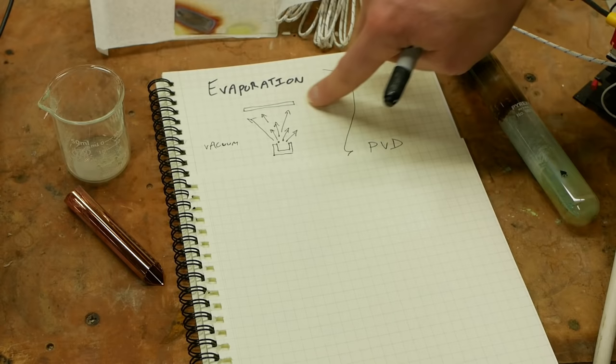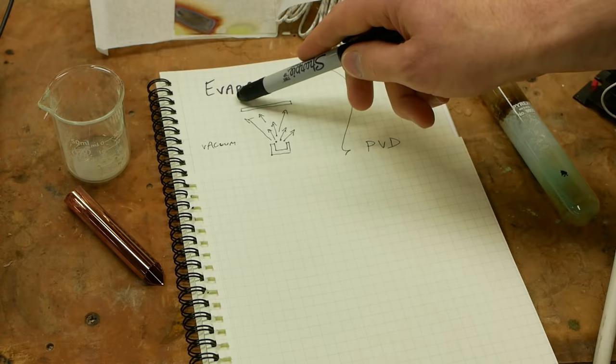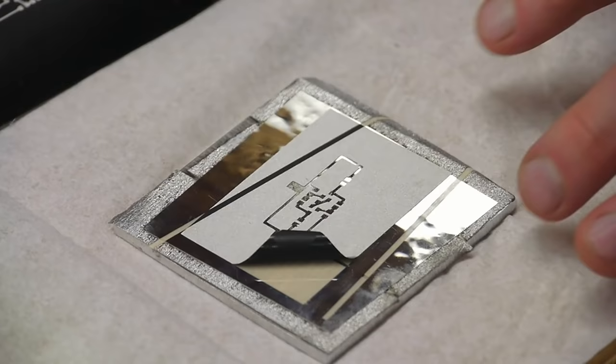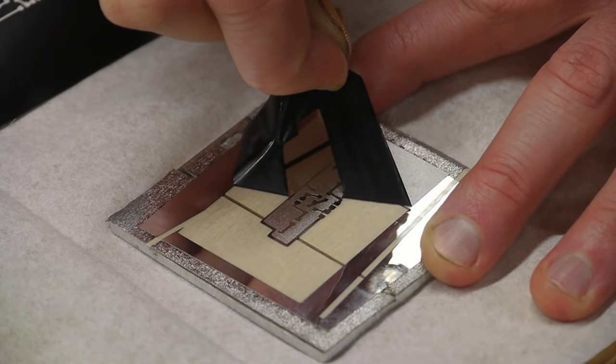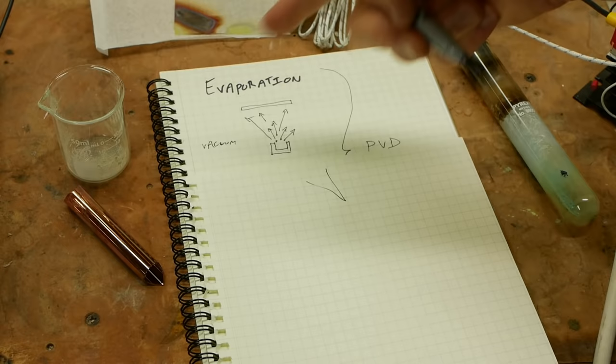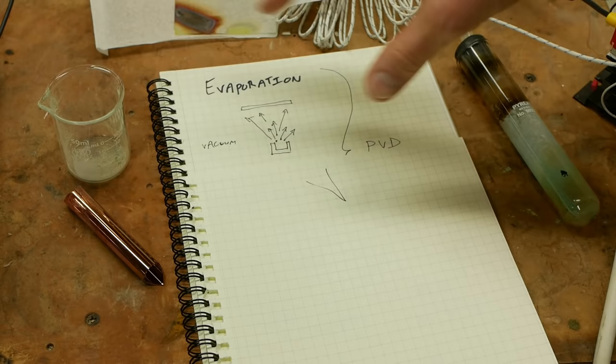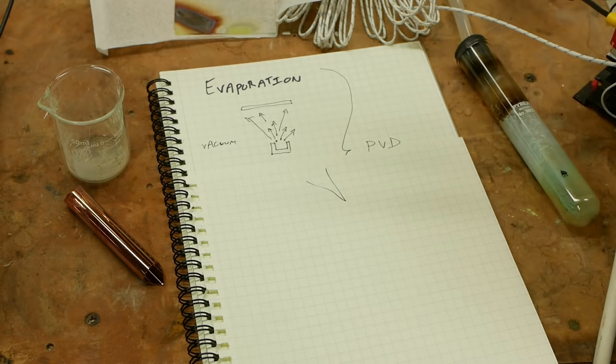This is very straightforward. It has to be done in very high vacuum. If you had any gas molecules between your source and your substrate, they would get in the way and cool down these hot molecules. Like if the molecule gets cold on the way here, it won't stick to the surface because it's already condensed and made sort of a metal cloud, as opposed to a metal layer on your thing. So you need really high vacuum. And another upshot of this is that there is no mechanism for these hot atoms and molecules to change direction.